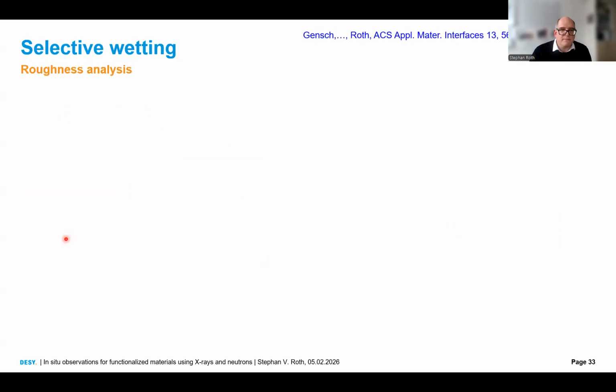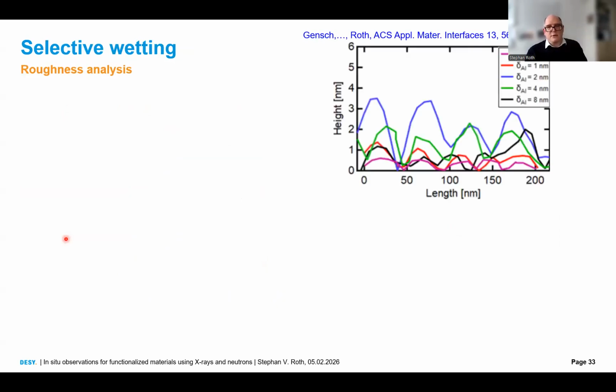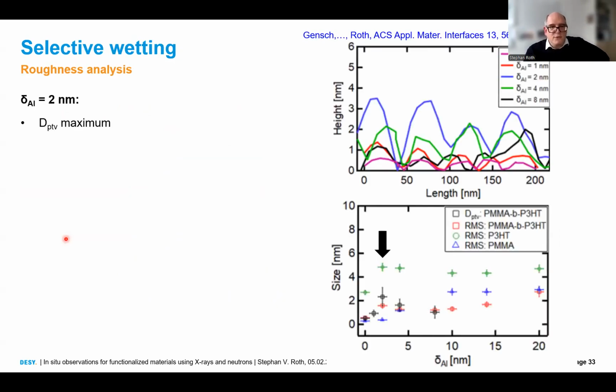And again, we also found here an aluminum intermixing layer, which we have explained in the last part with gold. When you have these diblock copolymers, the first thing you do is you have this nice structure, they are phase separated, and you deposit your metal, in that case aluminum. And you make an AFM image. We have 1, 2, 4 and 8 nanometer of aluminum.